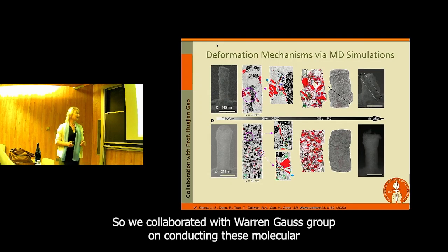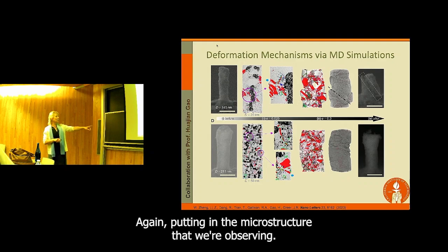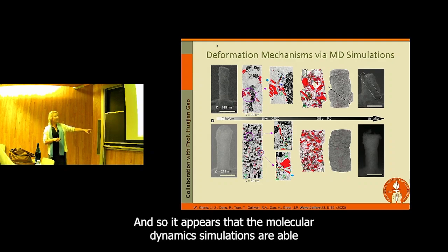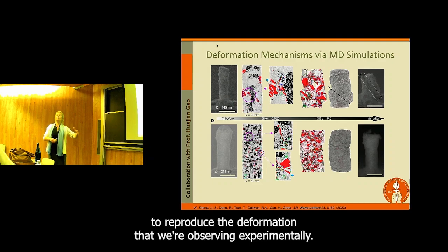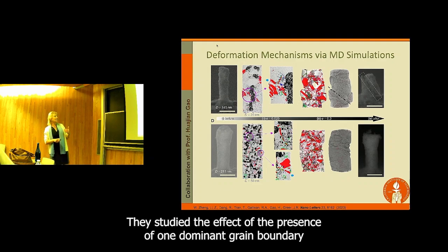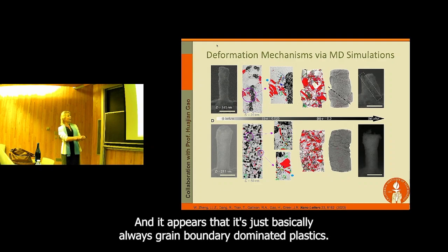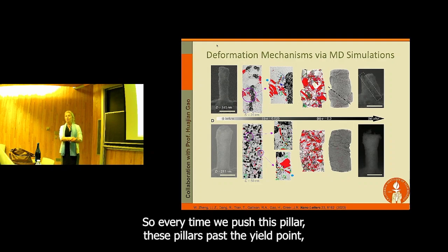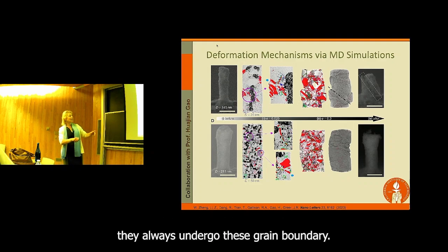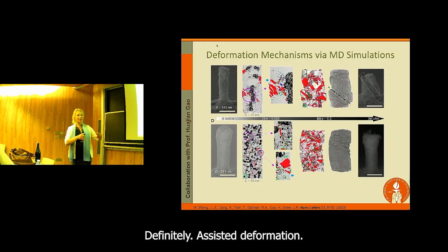We collaborated with Huajian Gao's group on molecular dynamics simulations, again putting in the microstructure that we're observing. It appears the simulations are able to reproduce the deformation that we're observing experimentally. They studied the effect of the presence of one dominant grain boundary versus not having it. It appears that it's basically always grain boundary dominated plasticity. Every time we push these pillars past the yield point, they always undergo this grain boundary assisted deformation.